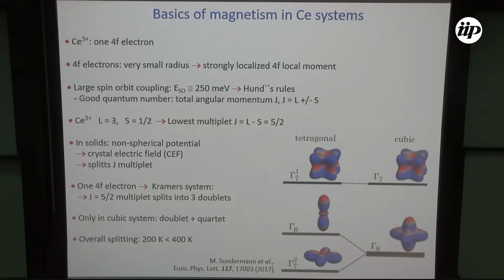Now in solids, one has a non-spherical potential, called the crystal electric field, that splits the multiplets. Because in cerium we have one f electron, this means we have a non-integer spin. This means we have a Kramers system, so in the presence of time reversal symmetry all states have to be doubly degenerate, and therefore we get a splitting into 3 doublets. Only in the case of very high symmetry cubic cases do we get a splitting into 1 doublet and 1 quartet, and that leads, as we will see, to some new possibilities. The overall splitting is typically of the order of 200 to 400 Kelvin.